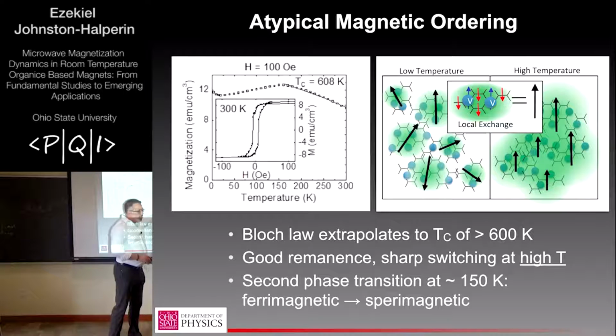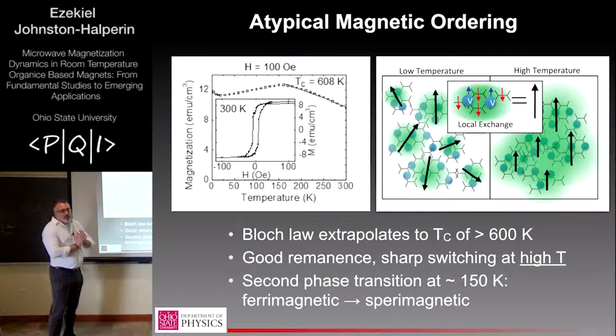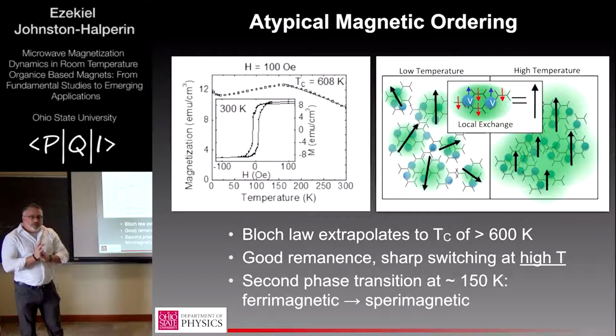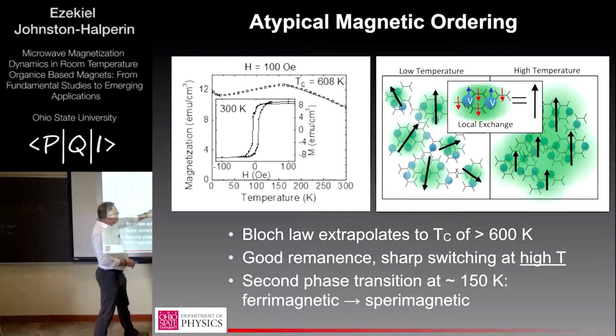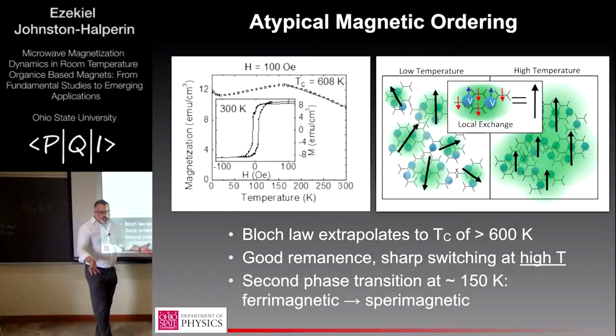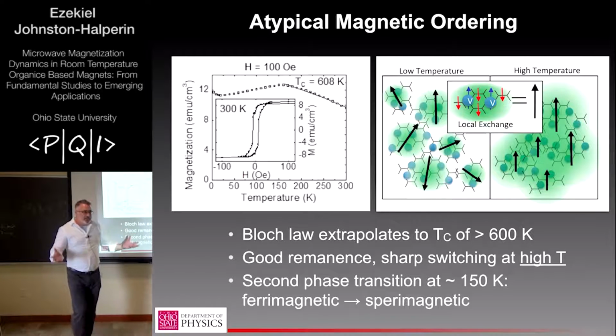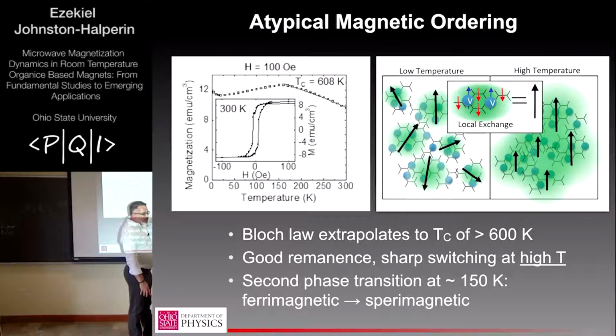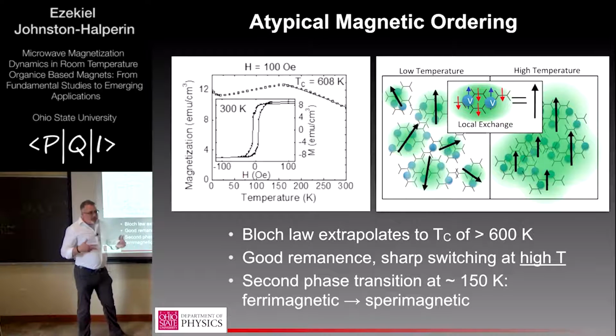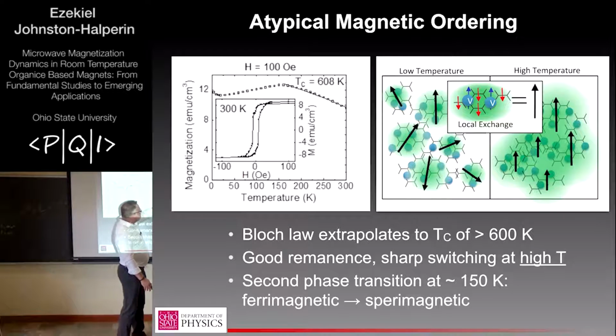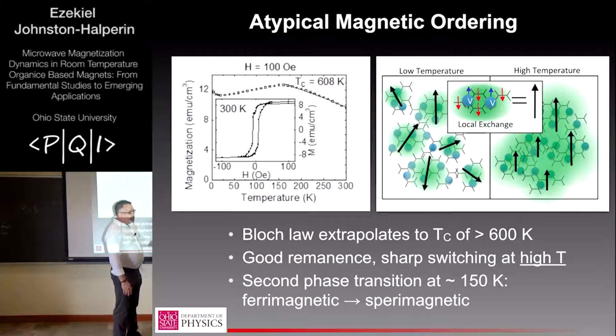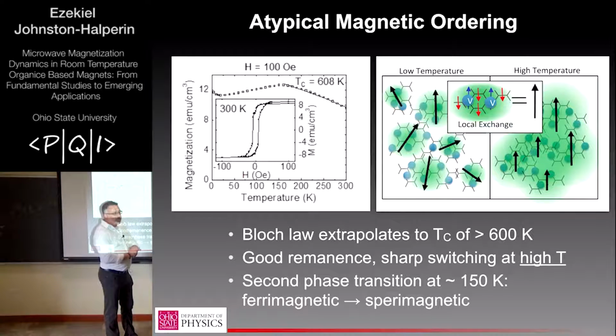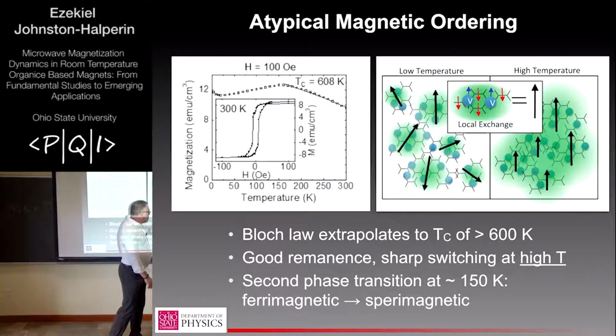So this is just a cartoon version of the carrier delocalization argument that I was putting forward, where I think as the carriers become, if this green color you can think of as the length scale of an electron in the system, as it gets colder and it freezes out, maybe to within a structural domain, then the film becomes more disordered, the net magnetization decreases, it becomes, one could say, glassier, although I think that's formally not correct, because there's still some local anisotropy within the grains. But qualitatively, that's probably a reasonable approximation, and then more uniform at high temperature.